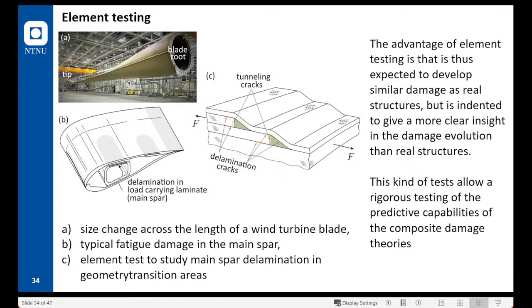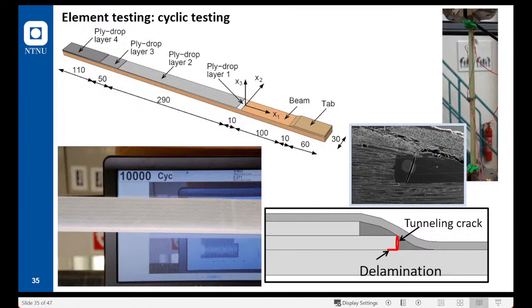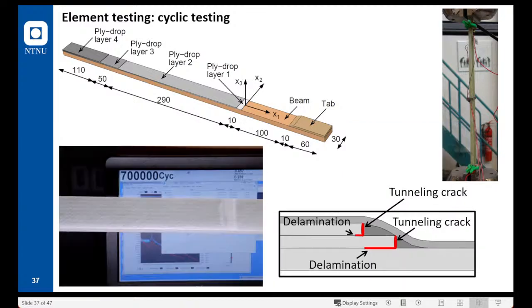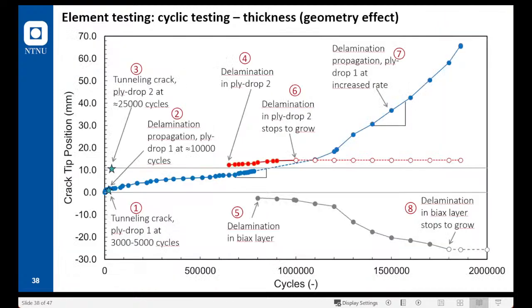When we design a component, quite often we are based on specimen testing. In practice, this is not always the best approach because we have many structural features that initiate cracks. So we have to move, and that's what happens nowadays, from component testing and specimen testing to element testing, which can represent structural design features in a simplified way. We have accurate load introduction, and we can follow how the cracks will evolve with the number of cycles. And we can make damage failure maps and identify which crack is the critical one.